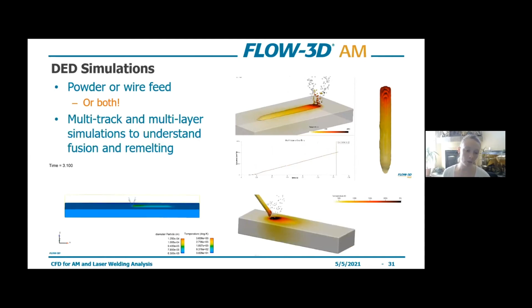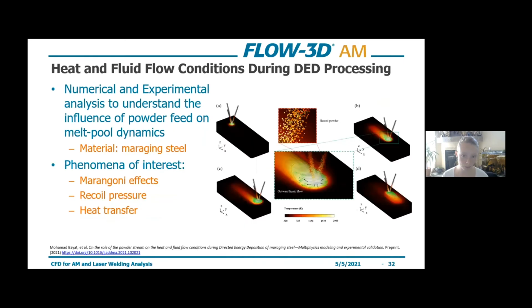And then we can also look at multi-layers in DED. So DED is a little bit more flexible in that the simulation runtimes are a little bit faster than, say, laser powder bed fusion. So we can look at a few different layers. The track width, the track lengths are a bit bigger, more in the few millimeters rather than usually less than a millimeter if we're doing a laser powder bed fusion simulation. So there's a lot of information to gain from modeling a DED process.